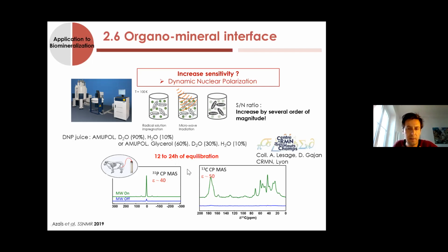In the case of bone tissue, after a certain time of equilibration, because it's not a porous sample, you have a very important increase in signal-to-noise for phosphorus and carbon. It means you multiply your signal-to-noise by 40 or 50. That's really a lot.